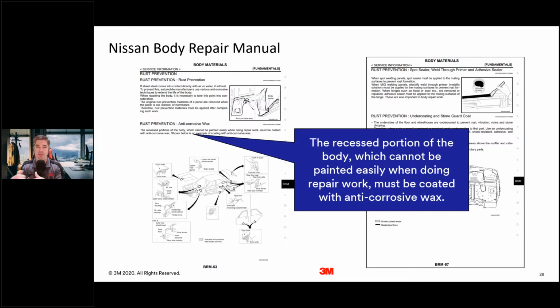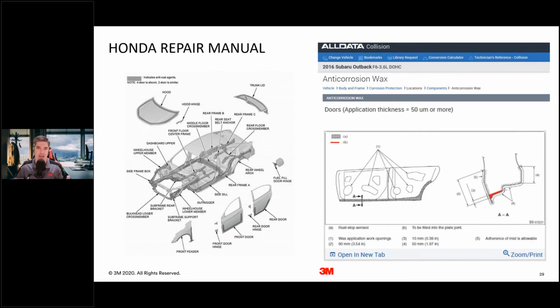Or if you come in with a cavity wax right after that, it might not allow them to dry properly, and it actually will plug the areas that are meant to be used to drain away water or prevent cavity wax from wicking in around our repair areas. So Nissan does a great job here highlighting that, in inaccessible areas, straight up cavity wax on bare metal, right? That's the best practice. And through our testing and our products, we've determined that is the best practice, very much so.